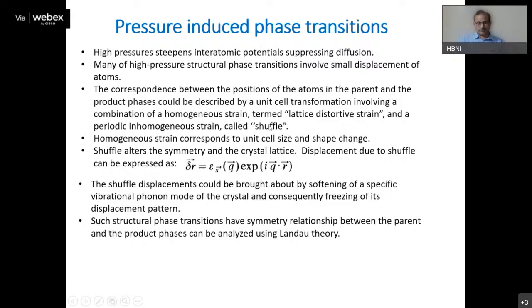Now when this shuffle kind of strain happens and the system goes to the transformed phase, they actually freeze to the new positions. So the corresponding vibrational mode should basically soften. This is the signature of the phase transition. Such phase transitions have a symmetry relationship, as I discussed earlier. So if there is a symmetry relationship, we can in some manner use Landau theory to analyze this phase transition.